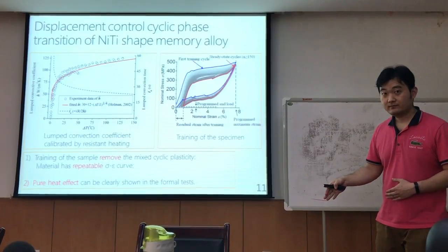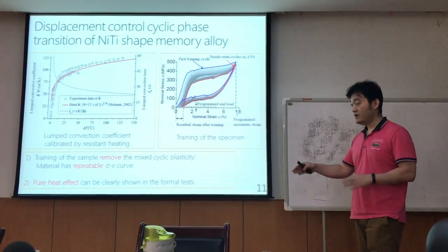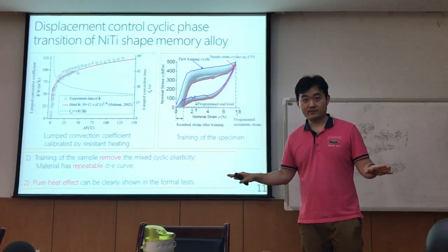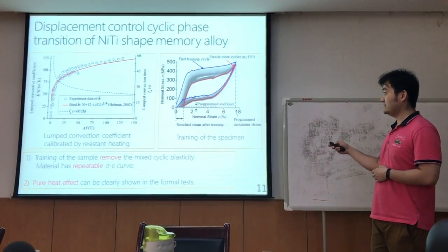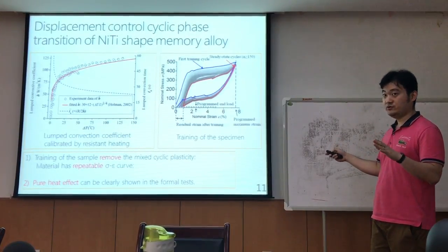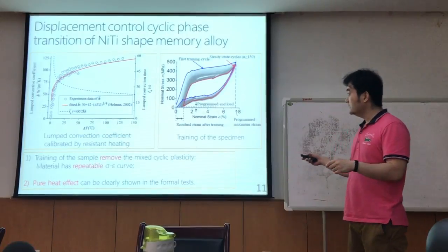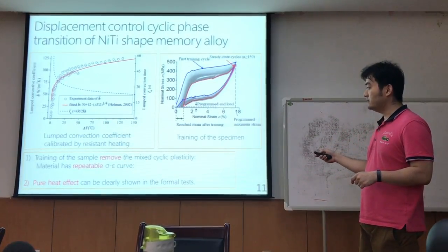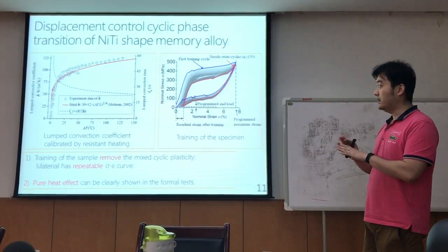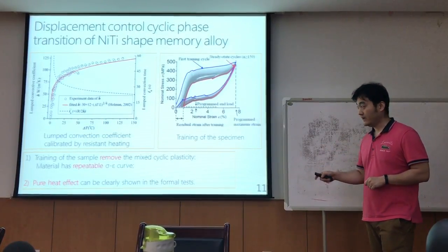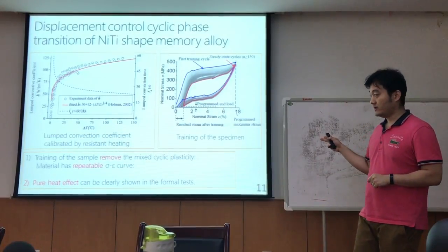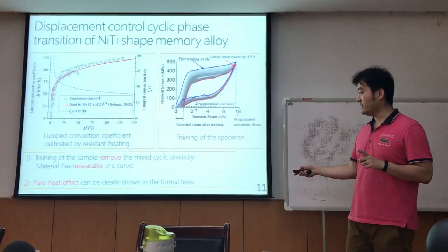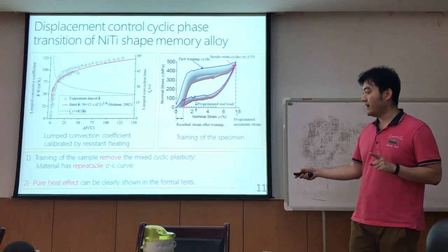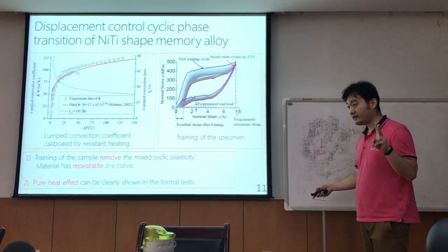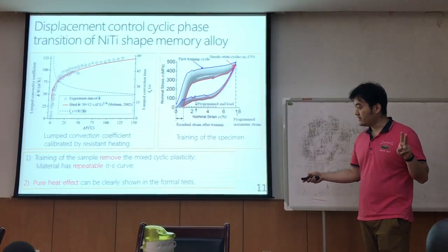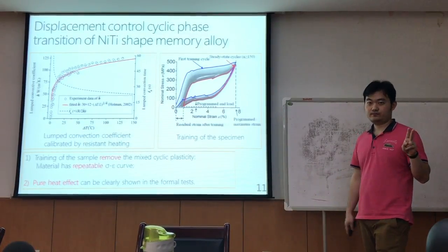And we do the training. As I told you before, we don't want cyclic plasticity involved, so we do this training process. This training process ensures that in our formal tests, the stress strain curves will no longer have cyclic plasticity. So the two objectives of this training process are, first, to remove the mixed cyclic plasticity so that the material has a repeatable stress strain curve. And second, in the later formal test, we can investigate the pure heat effect.